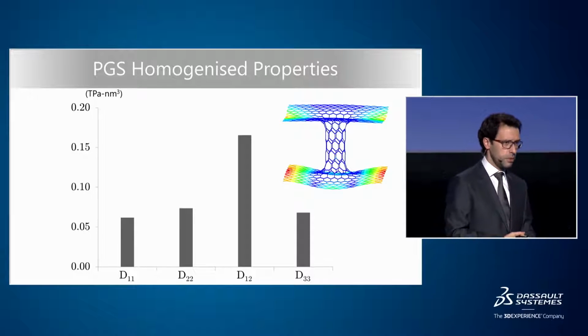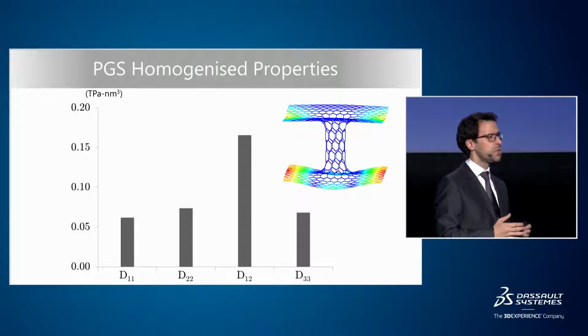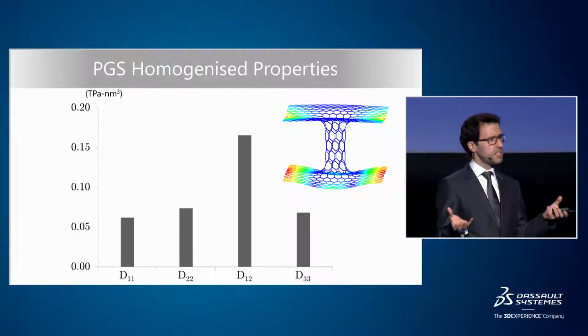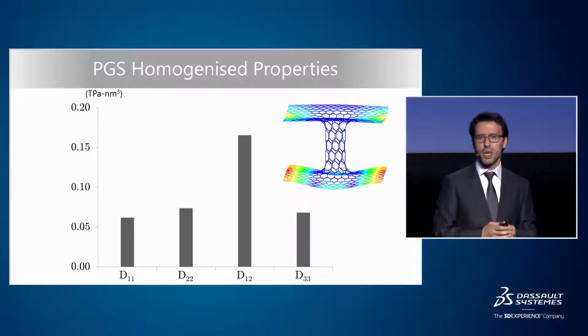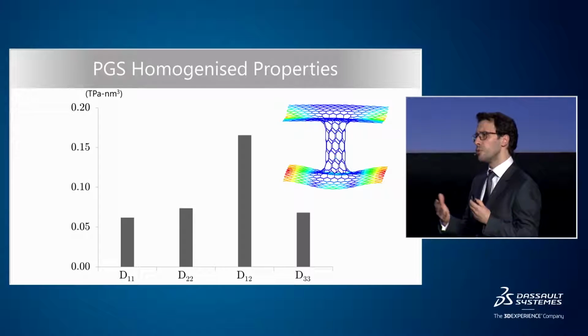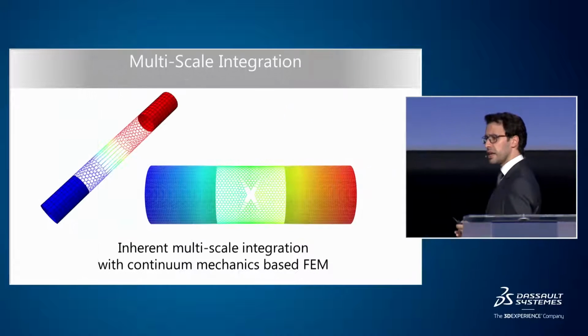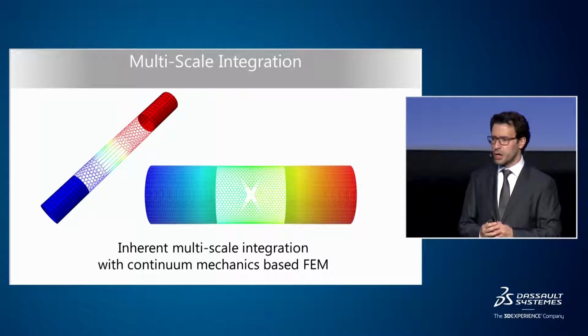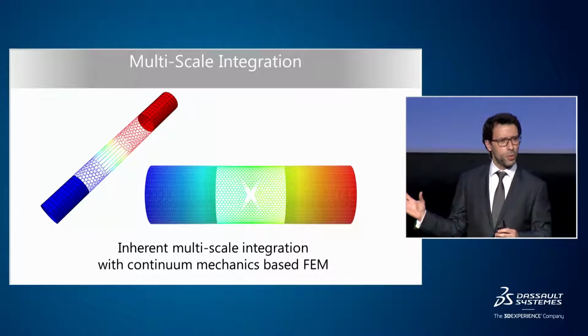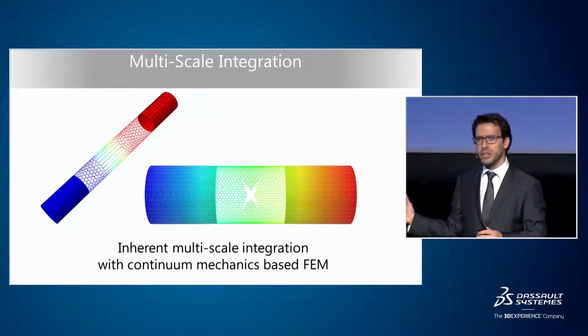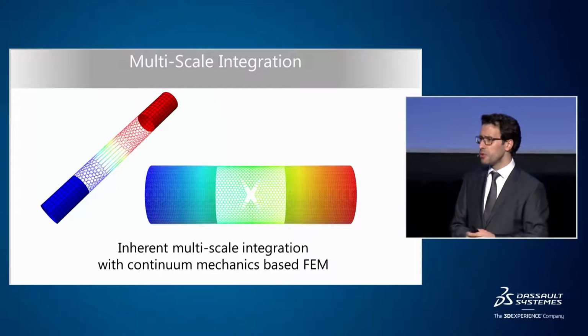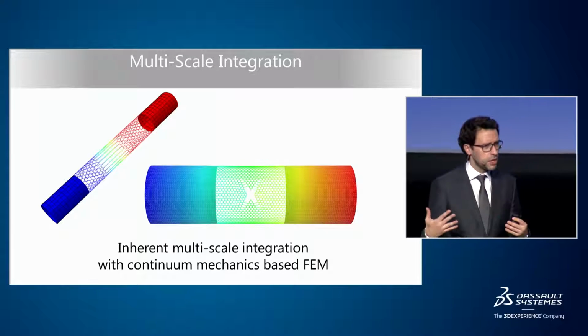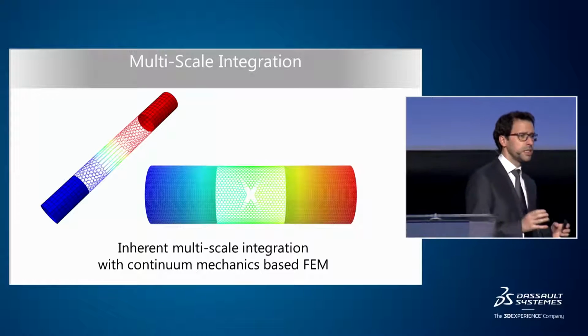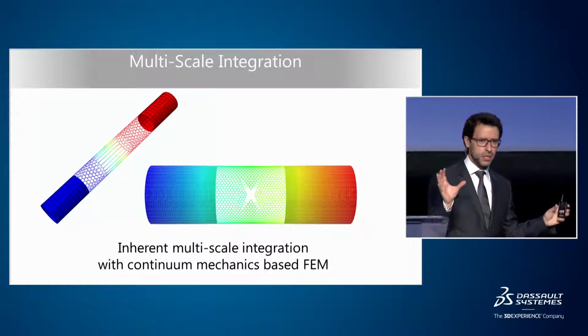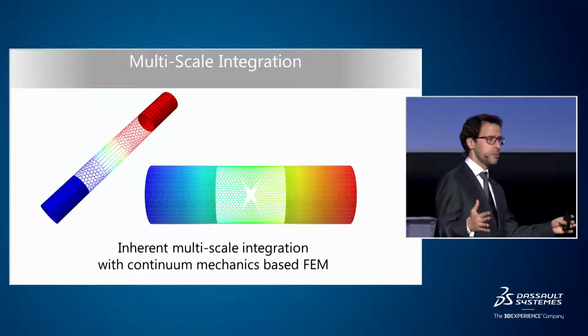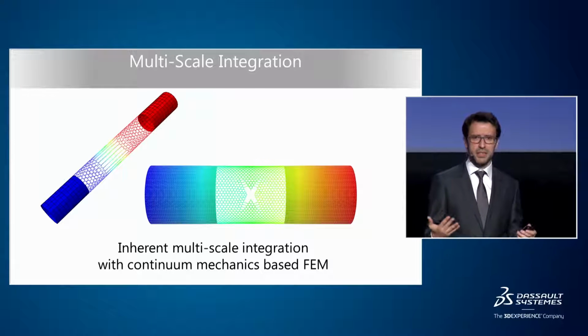But we are able to work out the boundary conditions for this case, and if you look at these bars, what they show is different coefficients of the D matrix, which represents the homogenized bending properties, in this case, of a pillared graphene structure. So we can get homogenized properties, and the implication of that is that we can have this type of simulations as shown currently on the screen, in which part of our domain is modeled with molecular dynamics inside Abaqus, and part of it with continuum shell elements. And some of you will have seen this type of multiscale simulations before. The thing that is quite unique about this one is that we don't have two different solvers communicating with each other. We have one single solver, one single system of equations simulating two different physics at the same time in a seamless way.